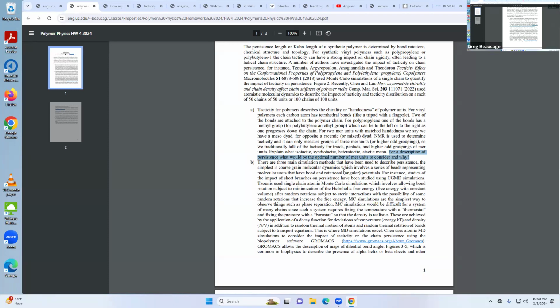So basically, if you're talking about 10 nanometers, whatever I said, like 40, you need 40. That's going to be the thickness of a crystal. So if you have to have 40 across the crystal and any kind of deviation in that, it won't crystallize. If you have iso, syndio, and then 30 more isos, that won't crystallize. So one monkey wrench will ruin it. That means you can only make the 30 thick crystal, which means it's going to have a lower melting point. It'll be gooier, right? So it changes the material.